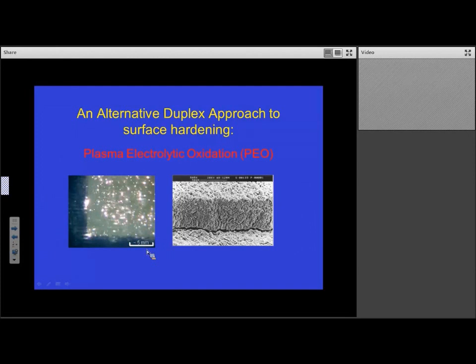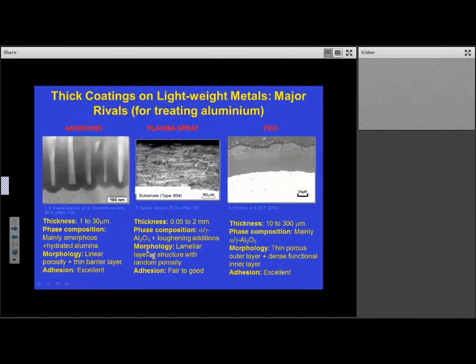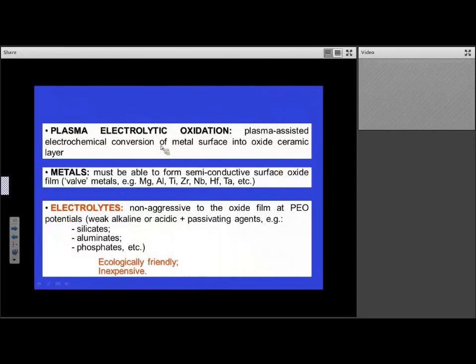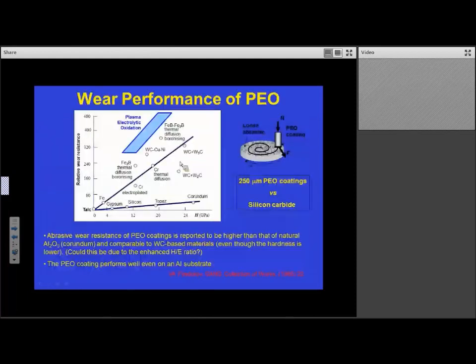And again, we have a world leader in this technology here at the university, Aleksey Yerokhin, who has developed this technique, which uses an aqueous electrolyte and is better than conventional anodizing in an acidic electrolyte, better than thermal spraying in many conditions, and produces a very dense coating. And the electrolyte is non-aggressive, safe, silicates, aluminates and phosphates are used. It's ecologically friendly and inexpensive.